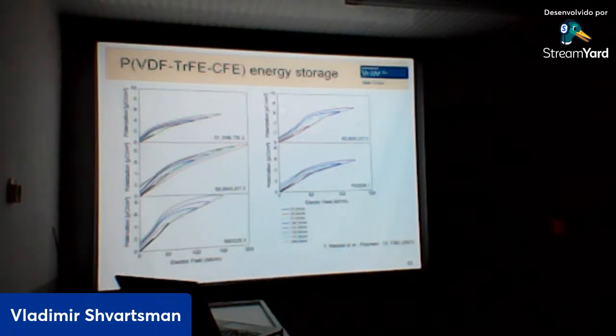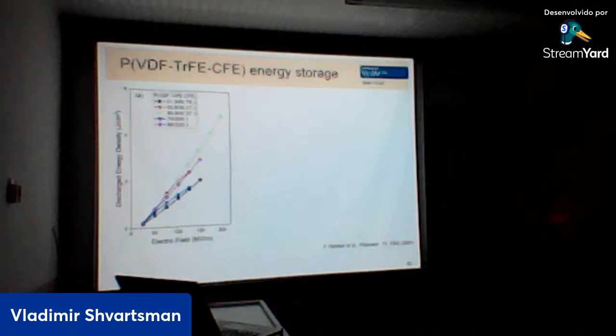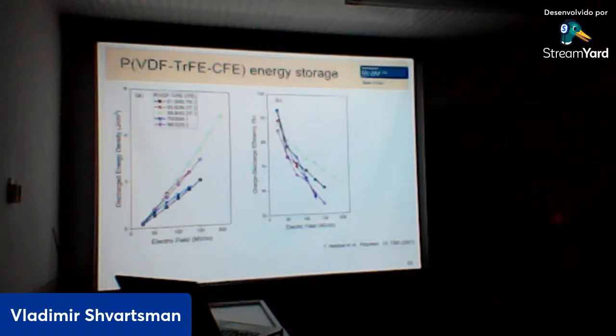The area between the polarization axis and field axis increases, but at the same time also hysteresis increases. As I said, we increase our stored energy and we also increase our losses simultaneously. So these are parameters for this polymer: discharge energy density, efficiency. For this terpolymer with 7% of CFE, at the field of 200 kilovolt per centimeter, we can reach the stored energy density of about 5 joule per centimeter cube, which is pretty good. And correspondingly, the efficiency will still be above 60%, which is also not bad.